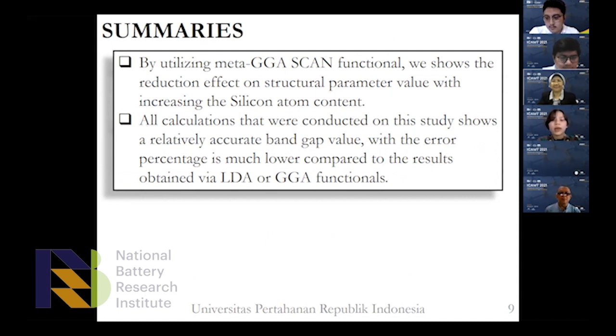By analyzing with the meta-GGA SCAN functional, we show the reduction effect on structural parameter values with the increase in silicon content. And all calculations conducted in this study show a relatively accurate band gap value, with the error percentage much lower compared to the results obtained via LDA or GGA functionals. Okay, that is all for our presentation. Thank you very much to the moderator and also all the participants in this session.